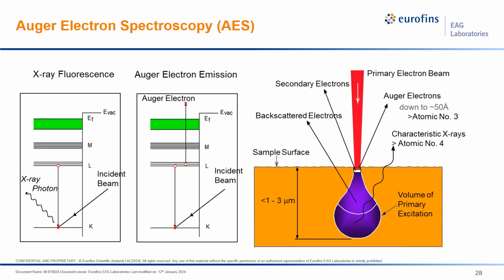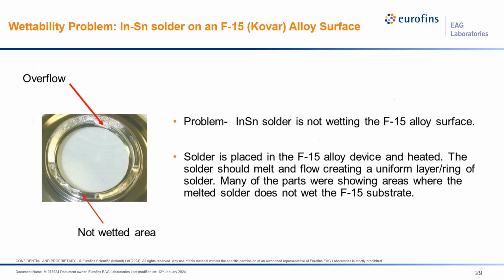So the point here is that we cannot detect hydrogen or helium. Same thing applies for a different reason to for XPS. But as I mentioned, the sampling depth in this cross-sectional view shows that only those electrons down to about 50 angstroms can escape the solid surface and get detected. Compare that to the backscattered or the photons, which have a much higher sampling volume. So often, work that comes to Auger started out in the SEM EDS lab, and nothing was seen. Thin film contamination was too thin for EDS.